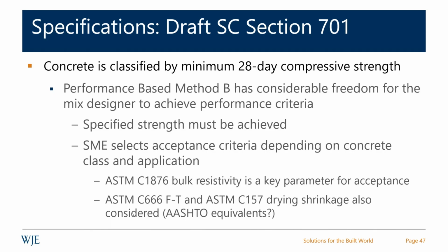Yep, you can have it at a couple of different times, as you do in some cases at 28 and 56 days, for example. Basically, you're heavily relying on the bulk resistivity, which is a good test. But note what I said, that as you move towards more exotic systems, you may find that the bulk resistivity is not applicable. Another example is if you use colloidal silica as an additive, they will say that it changes the pore solution conductivity and also makes the bulk resistivity not an applicable test. So something to consider. And then you're looking at other durability performance tests.